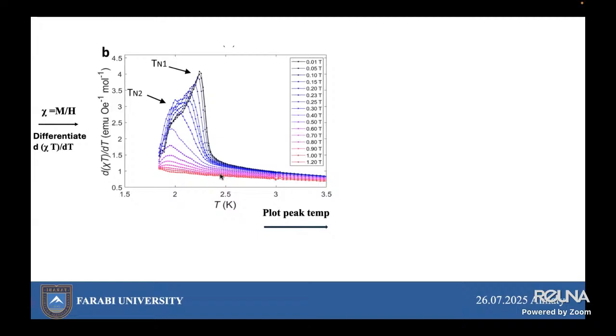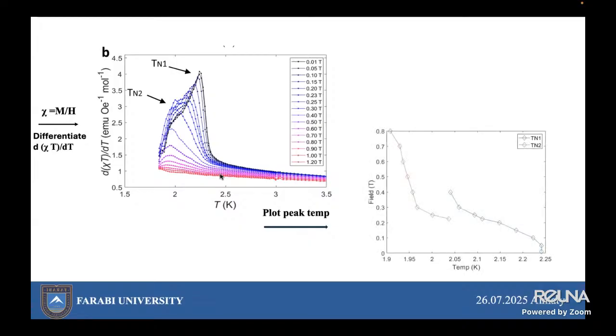Another shoulder-like feature is visible at 2.0 Kelvin, denoted TN2. The second transition suggests a more complex magnetic structure, such as multiple antiferromagnetic sublattices or competing interactions. It decreases from 2.25 to 2.05. And here you see a picture that plots the peak temperatures.